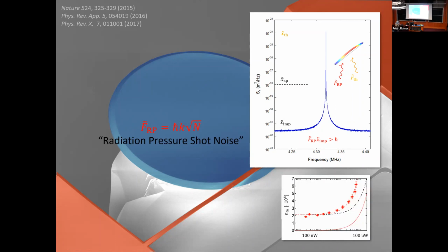So we're one of the first people to actually see this type of effect a long time ago with a system like this. You can actually take that measurement and feed it back using radiation pressure or what have you. We just use radiation pressure with a time delay to actually cool the mechanical resonator. This is called cold damping. If you did that, you damp the mechanical oscillator. The area underneath that peak corresponds to the energy of the mechanical oscillator. We can cool it down by many orders of magnitude by this method.